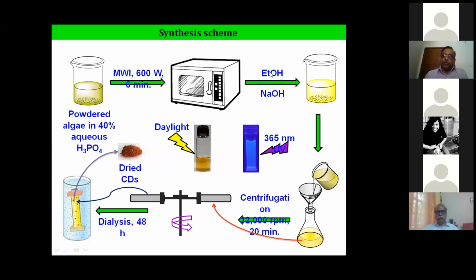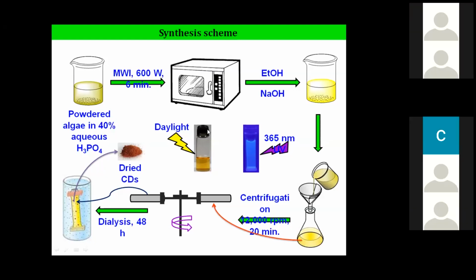Add ethanol and sodium hydroxide, then you can see the formation of the dots. You can centrifuge them, filter it, and after filtering, the purification procedure is dialysis. That is very important. Otherwise, you get a lot of organic molecules going into the solution. So you have to remove all organic molecules, retaining only the smaller size quantum dots into these dialysis bags. This is an important step when you synthesize carbon dots. So you generally follow this methodology of synthesizing, separating, and purifying it. These are the steps we followed to get the carbon dots using microwave.